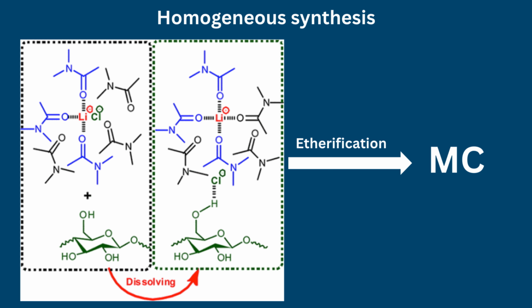In contrast, homogeneous synthesis dissolves cellulose in solvent systems such as dimethylacetamide/lithium chloride, quaternary ammonium hydroxides, or NaOH/urea solutions before etherification. Uniform accessibility of hydroxyl groups leads to a more homogeneous distribution of methoxy substituents, producing materials with improved water solubility but generally weaker thermoresponsive gelation.